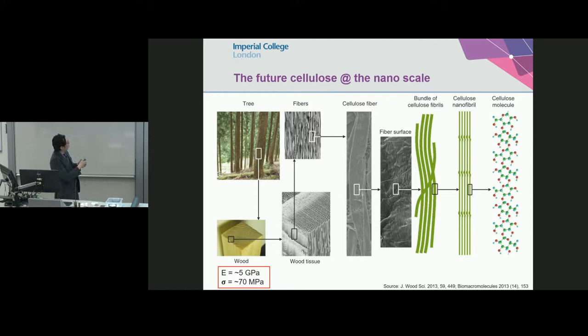But if you're able to go all the way down to this scale down here, this cellulose nanofibril scale, suddenly the performance of that nanofiber goes up to 100 gigapascal, which is beyond the performance of glass fibers. The strength here will easily go up to 1500 megapascal. And again, that is a lower bound. The upper bound is about 6000 megapascal.